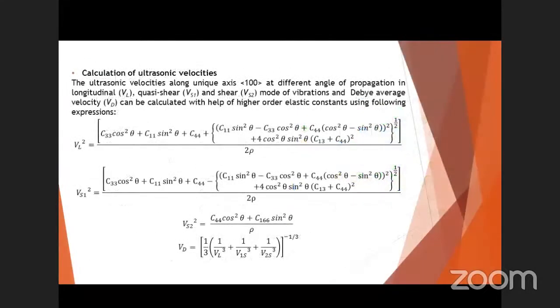These are the ultrasonic velocities in different directions. We have taken the unique axis of the hexagonal crystal, and we have calculated velocities: longitudinal velocity, quasi-shear velocity, and shear velocity, and then we have found the Debye average velocity. These are the formulas. Here theta is the angle with the unique axis, and these are C33 and C11. All others are the second order elastic constants.